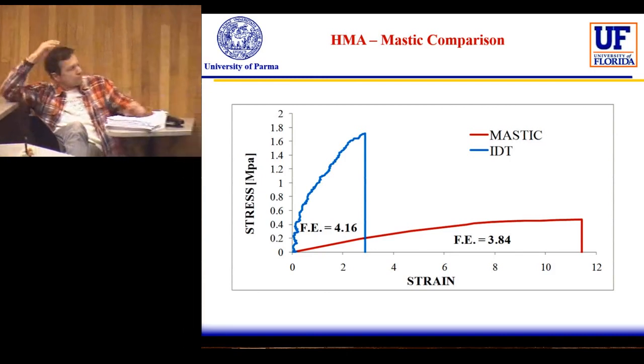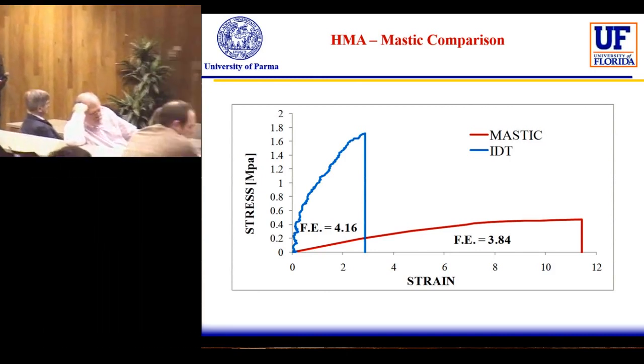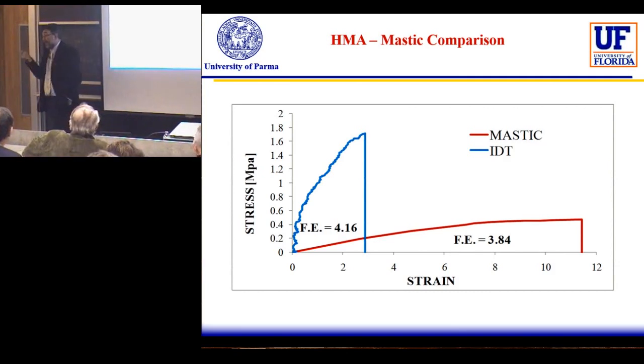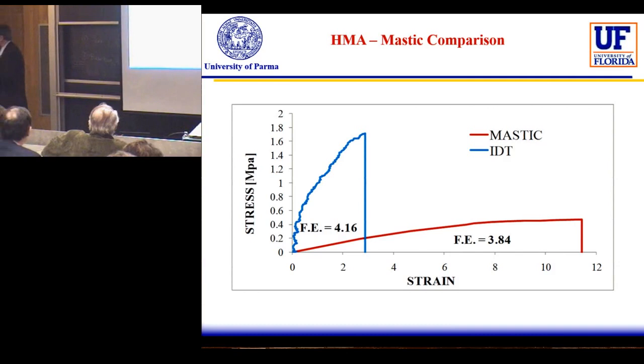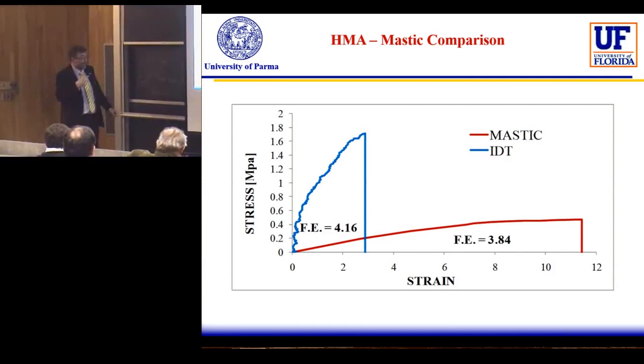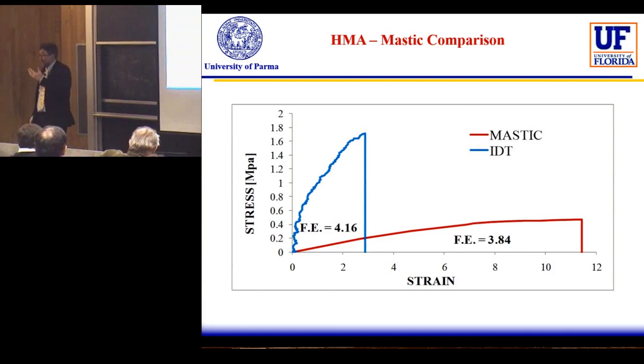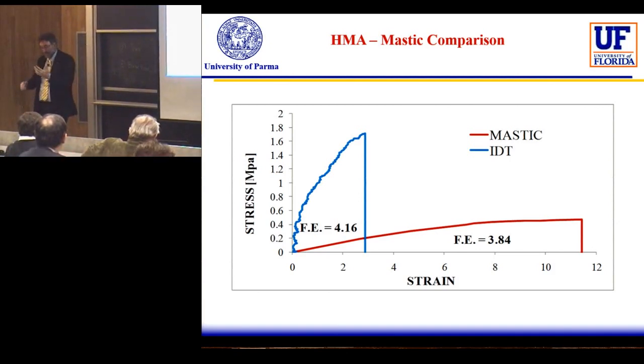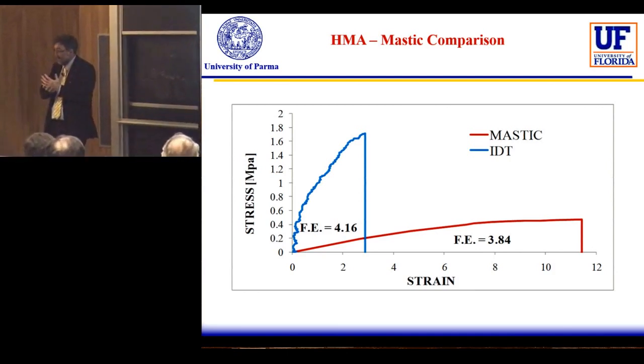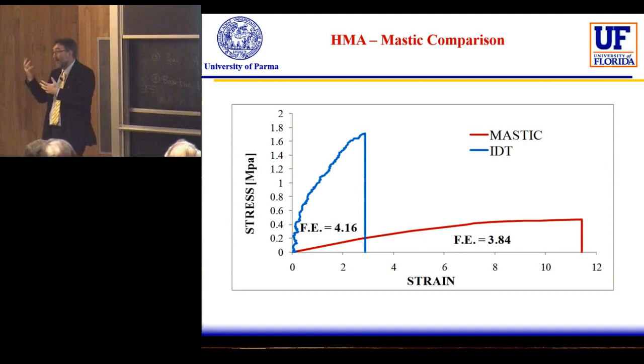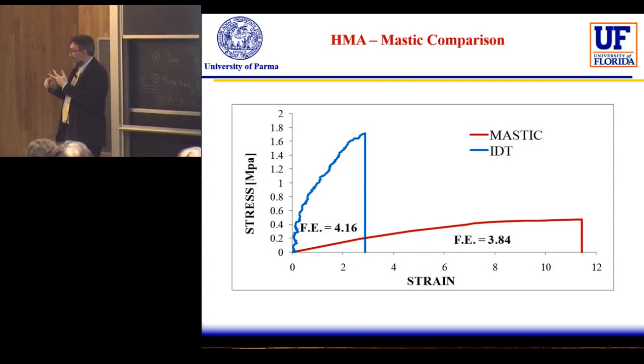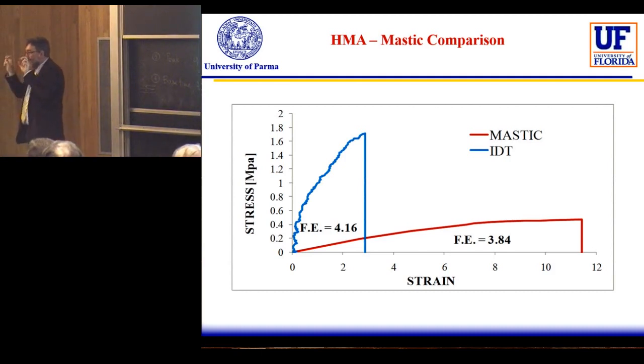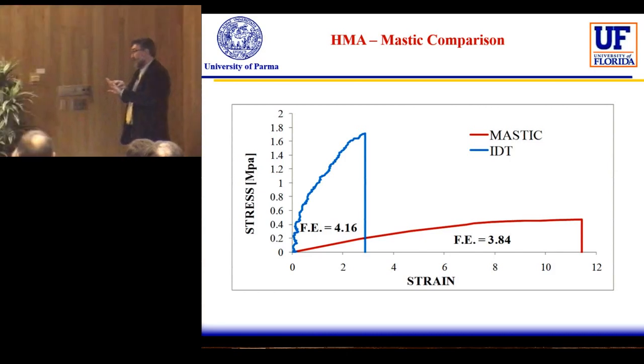Generally, what we did here is to change the physicochemical characteristic. One of the hypotheses is an unclear situation. We have different theories around at the moment. For example, in the case of the hydrated lime, one of the hypotheses behind the different behavior is that due to the high surface of the hydrated lime, there is an interaction with the oil in the bitumen, which is traditionally considered composed of oil, asphaltene, and the other families. The oil, the so-called volatile part of the material, is the main actor of the so-called aging.